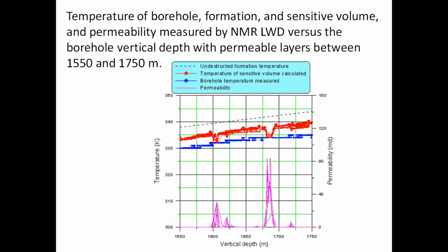Here is the temperature of the borehole, formation, and sensitive volume. Borehole is blue, sensitive volume is red, and the black dashed line is the temperature of virgin formation estimated from the geothermal gradient, and also shown here is the permeability from NMR logging while drilling data. You can see that for permeable intervals, the temperature of the borehole and the temperature of the sensitive volume are almost the same, but for low permeability intervals, there is a difference.